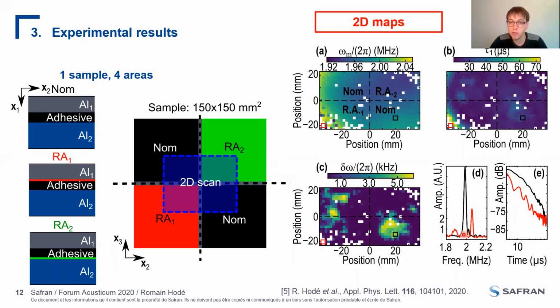But we have not observed this frequency around 1.9 megahertz on the previous samples, and this needs to be fully explained. Maybe it can be due to the migration of the release agent during curing, or also to residual stresses in the bonding due to the different areas. But these are questions that need to be addressed in the future.